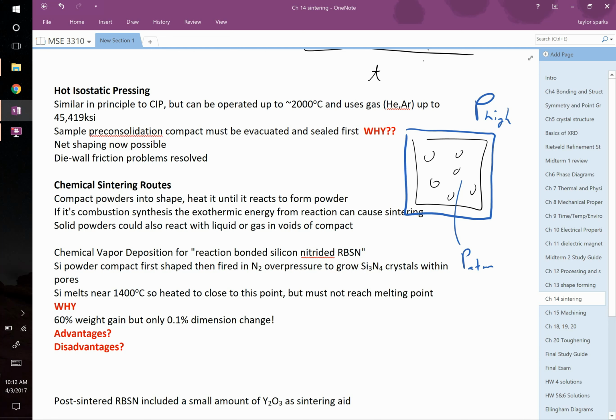Barrett? Why doesn't the glass layer break, because it's squeezing this, right? That's a good question. It's at higher temperatures than the glass. It's not in its glassy regime. It's way above its glass transition temperature. So the glass, I don't know if it's a thin molten layer or what it is, but it's not brittle for sure. I don't know exactly what's happening in that material. I know that it's glass that they use, but you're way above its melting point. So I don't know if it's like a thin liquid or what it is, and how it stays impermeable. It's a great question.